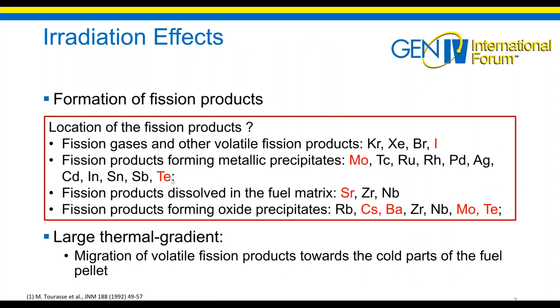So the fission products formed can be classified in different families, because every fission product has its own behavior. You can distinguish four families. The first one is the fission gases and other volatile fission products like iodine, for example. You also have the fission products forming metallic precipitates like molybdenum or tellurium. The third family is the fission products dissolved in the fuel matrix like strontium. And finally, the fission products forming oxide precipitates like cesium, barium, molybdenum, and tellurium.